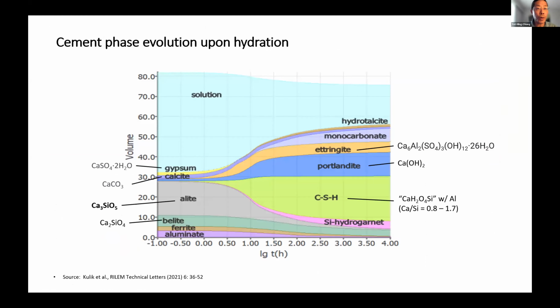This chart shows you what happens to cement, which is the mix of materials we have on the far left here, right? By volume. The vertical scale is volume. The horizontal scale is time, hours on a log scale. And the source for this plot you can see at the lower left here. And I've annotated it a little bit just to highlight the gray phase alite here. That's the tricalcium silicate. Okay. And so as you watch the evolution, the reason the volume increases of the solids is because it's hydrating. Okay. As the aqueous solution is producing solids that are hydrates.